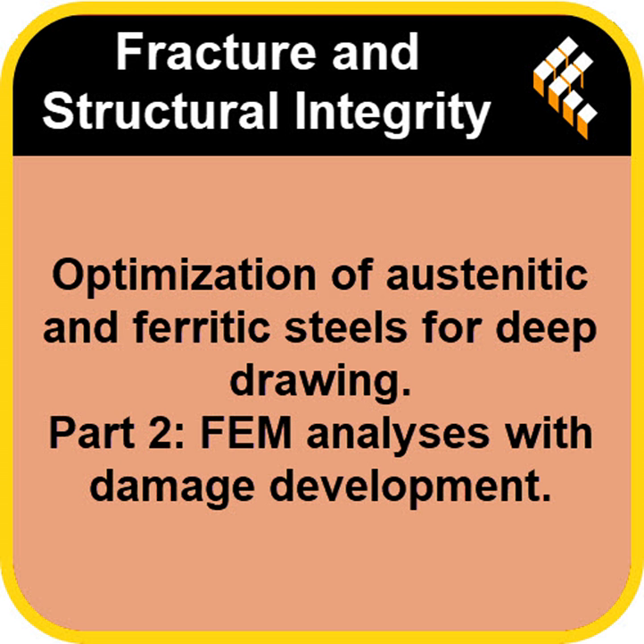So what does this all mean for us looking at these finished stainless steel parts? Here's a final thought. We saw that with the optimized process, the good lube, the stress at failure actually hit 1200 MPa, significantly higher than the 1000 MPa seen in the poorly lubed case. Does optimizing the process so successfully actually push the material much closer to its absolute physical limit? Does it make the process hyper-efficient, but maybe also more sensitive, more on the edge, vulnerable to tiny variations in material batches or temperatures? Something to think about next time you see a complex, deep-drawn stainless steel part.